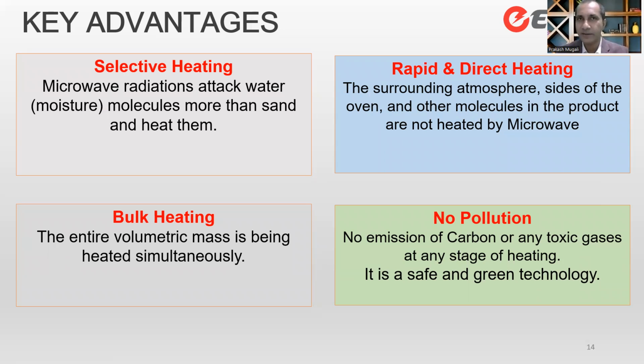And also, in spite of that, you will only see a dry surface, but there may be moisture left in the core. That's why another way of testing is you take out the sand in the core and then you test, right? So to check how much moisture has gone out.